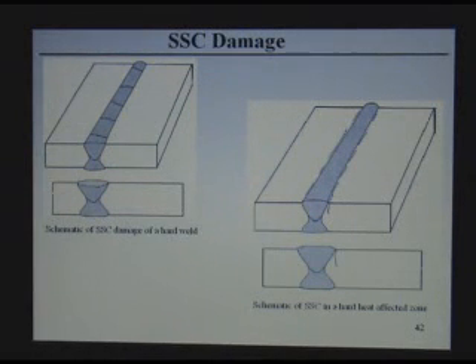Hydrogen also, from the H2S, sulfides can cause sulfide stress corrosion cracking. This is a function of the hardness of the steel. That's why we always recommend a maximum of 200 Brinell, and we require stress relieving carbon steel to avoid having high stresses and hardnesses, to avoid this mechanism of sulfide stress corrosion cracking. Here is another sulfide stress corrosion cracking in the heat affected zone.